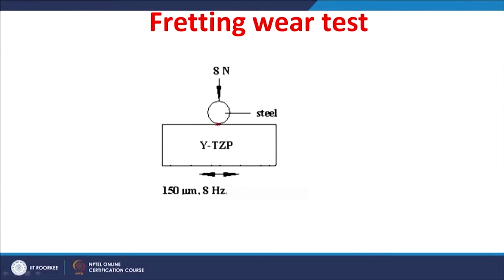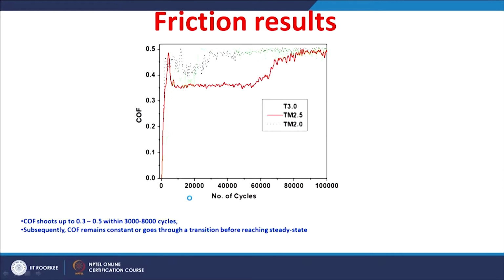So, keeping all the parameters constant, this fretting is a small amplitude oscillatory sliding movement. The oscillation is around 150 micrometers and the frequency of the oscillation was 8 hertz, and this was conducted for a number of cycles up to 100,000 cycles.